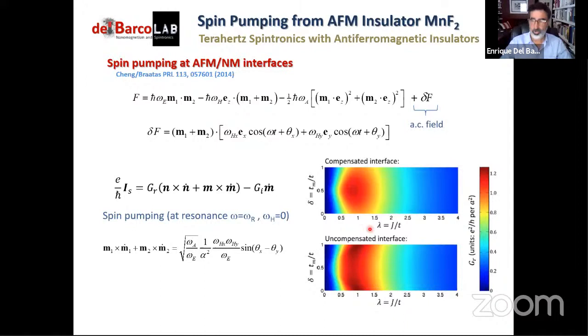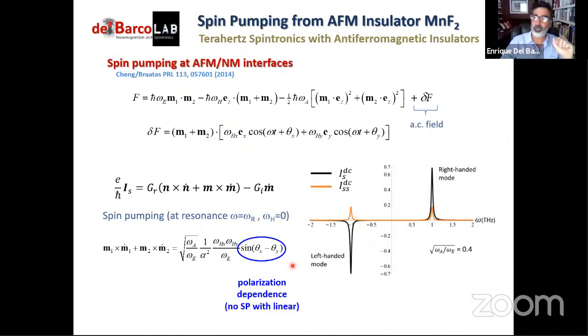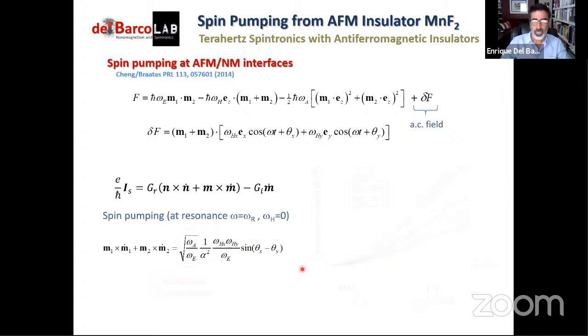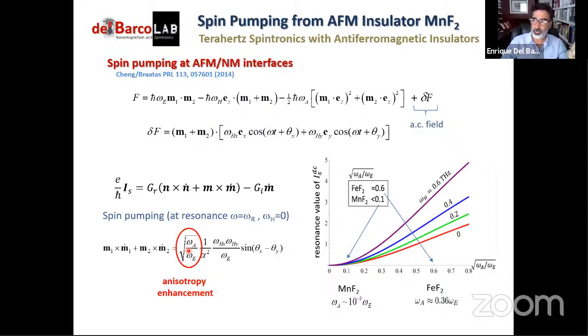But very interesting in antiferromagnets, and this doesn't happen with ferromagnets, is the fact that the polarization nature of the mode sets whether you have spin pumping or not. So only circularly polarized antiferromagnetic dynamical modes will lead to spin pumping. If the mode is linearly polarized, it won't generate any spin pumping. And the other thing is that the spin pumping effect is going to be proportional to the ratio between the anisotropy and the exchange fields. And this can vary substantially.